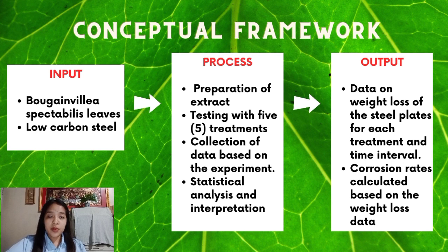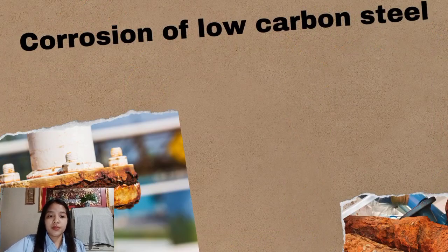The weight of the low-carbon steel in the extract was observed during the standard time limits of 0 minutes, 5 hours, 15 hours, and 24 hours at the laboratory temperature of 30 to 33 degrees Celsius, or room temperature. The researchers then analyzed the data and drew conclusions based on their observations.